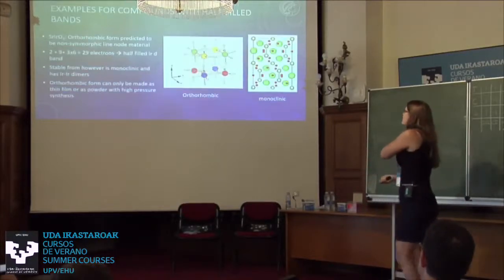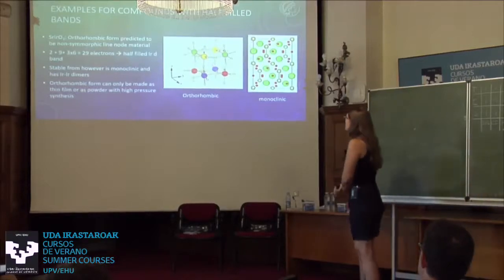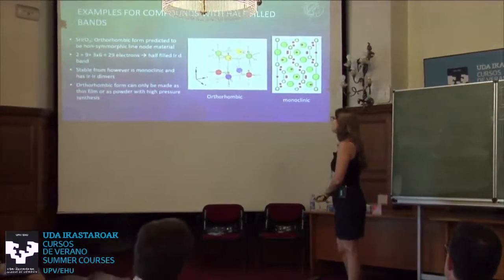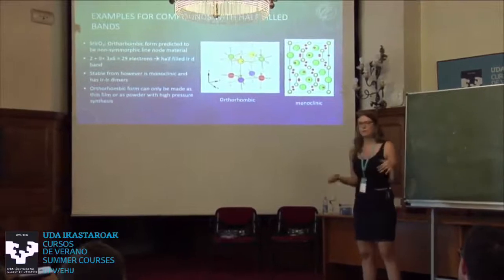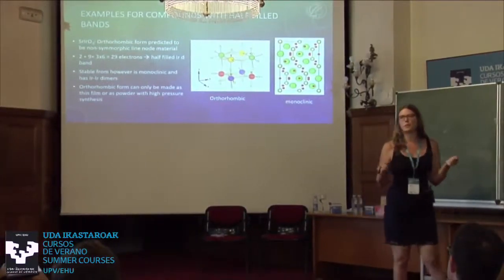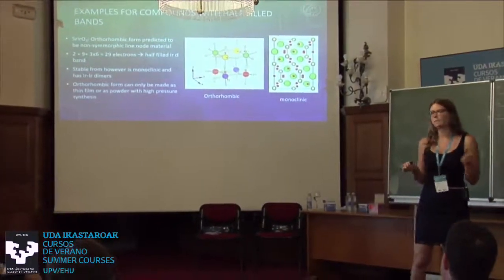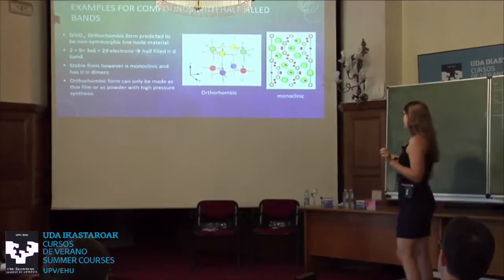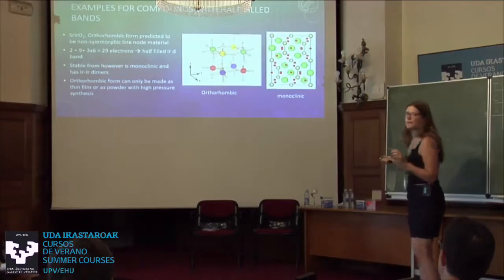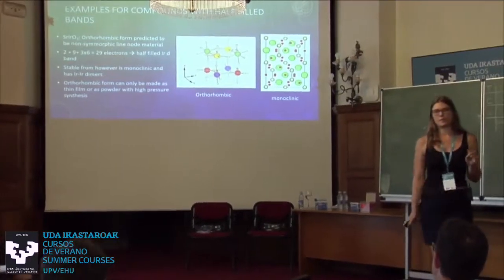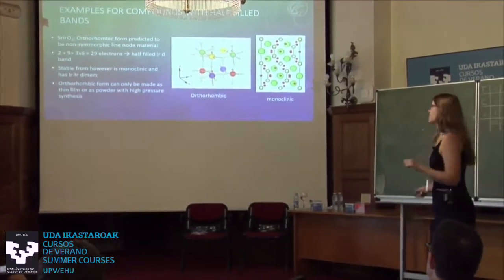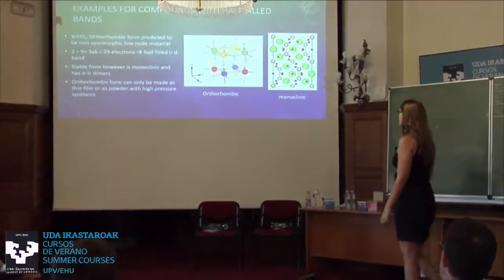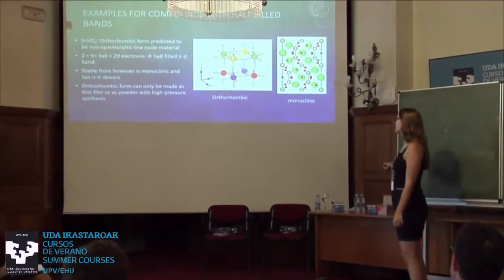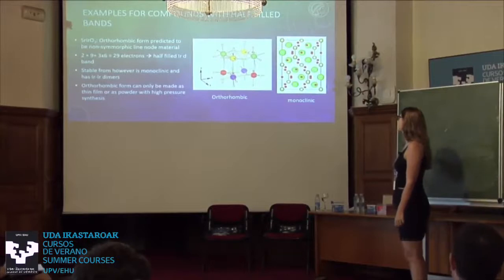And so this gives me the example of strontium iridate, which is currently a very heavily studied compound, predicted to be a non-symmorphic Dirac line node material. And if you count the electrons here, you would also figure out that it has a half-filled iridium d band. And so strontium iridate actually forms 2 different crystal structures, this orthorhombic one here and the monoclinic one here.